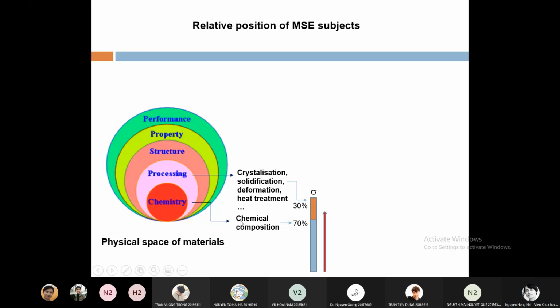So, beginning from chemical composition, via the processing, we make the material with desired structure and microstructure. What is the microstructure of the alloy? It is the size and morphology of the grain, crystal grain, and lattice defects. So mainly size and morphology of the grain. Grain can be fine or coarse, and morphology of crystal, maybe dendritic, thick, and so on.